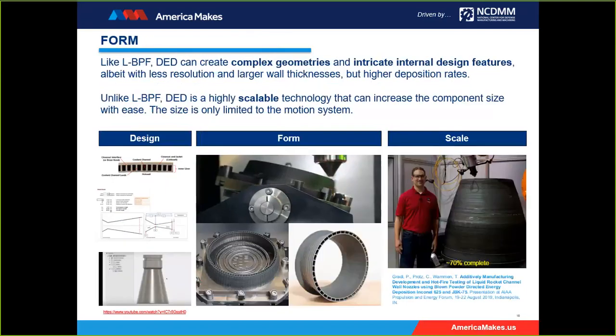Focusing on form first, with DED, you can certainly create complex geometries and intricate design features with wall thicknesses regularly around 1 to 3 millimeters. The larger your spot size and layer thicknesses, the faster your part can be made. And with the size of the part only limited by the motion system, the technology is highly scalable. The technology can be integrated onto existing motion system assemblies. So you could yourself integrate the technology used in DED into a motion system that you currently have in-house and have yourself a directed energy deposition system. The images show how you can design for additive, achieve a part such as a rocket nozzle, and eventually scale up. To the right is a large DED, I believe it's a wire arc process, and NASA usually incorporates it for a lot of combustion liners and the rocket nozzle downstream.